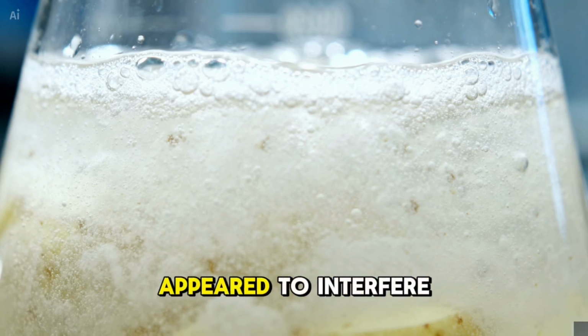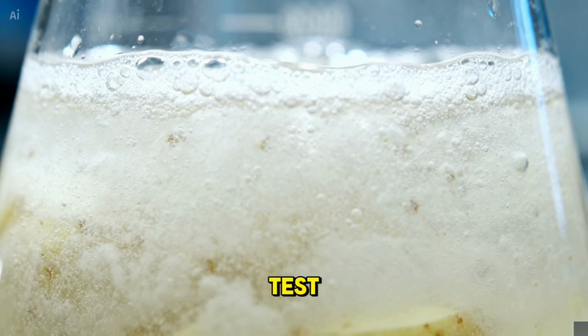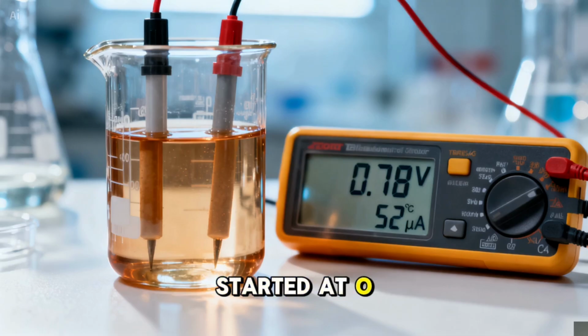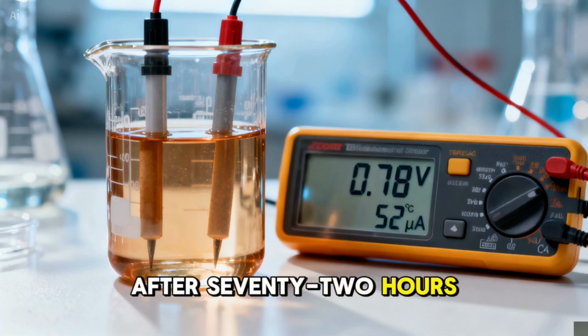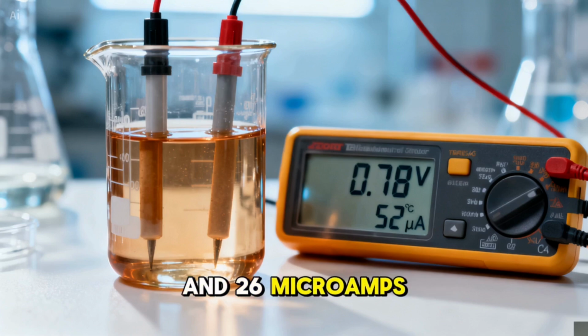Potato water. Weakest initial performer of the six, started at 0.49 volts and 24 microamps. The significant turbidity from starch compounds appeared to interfere with ion mobility, dragging down the performance throughout the test. Vinegar electrolyte started at 0.78 volts and 52 microamps. After 72 hours, down to 0.44 volts and 26 microamps. Decent initial performance, moderate decay.